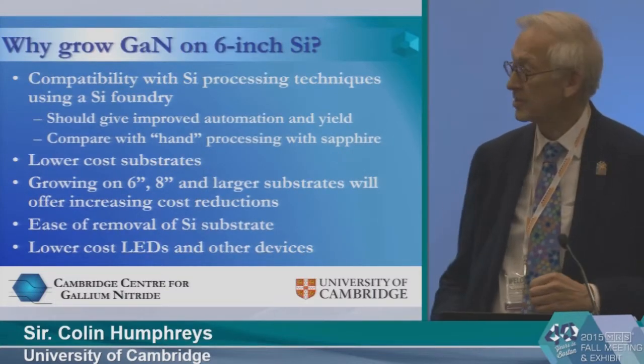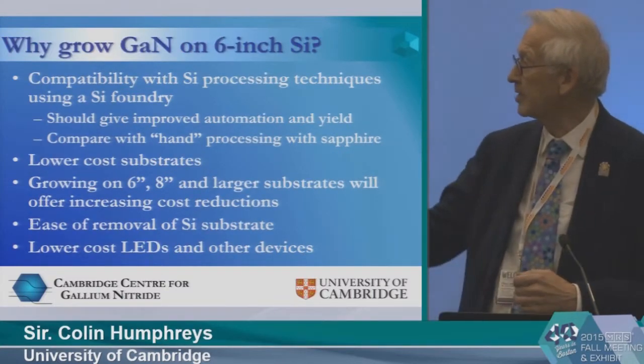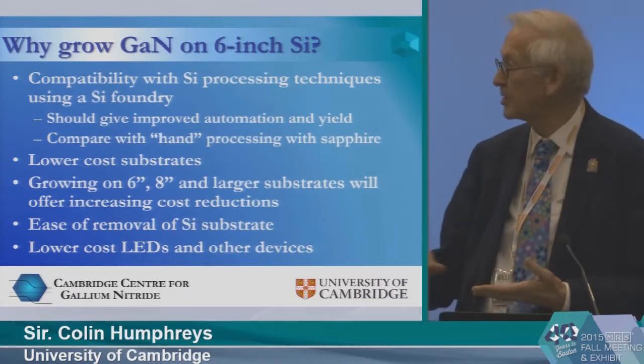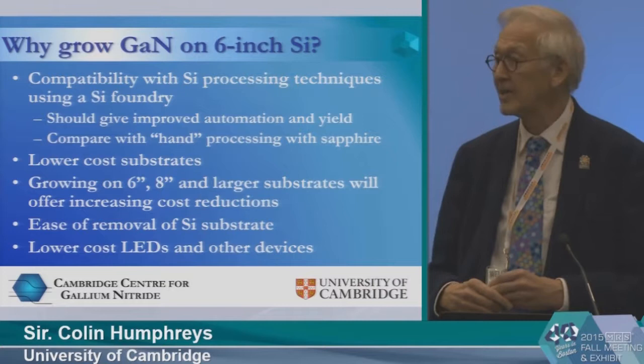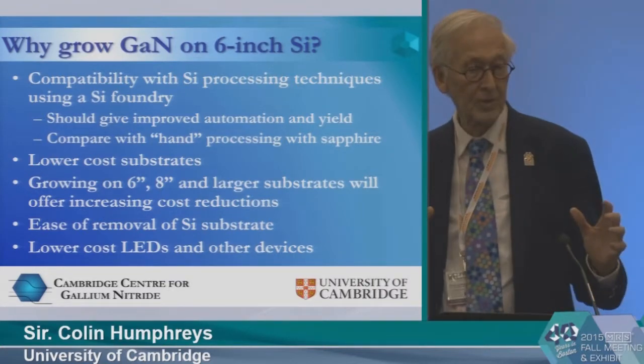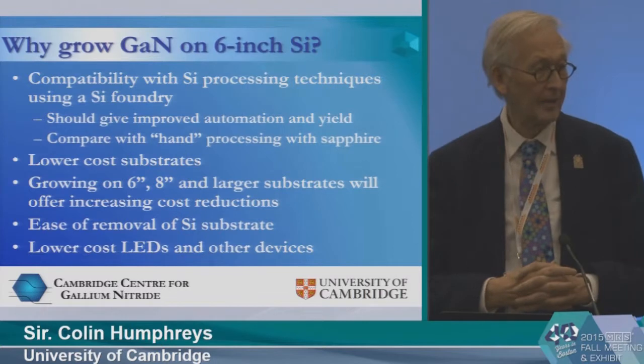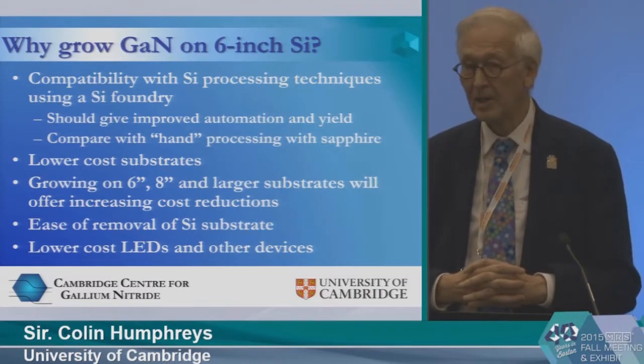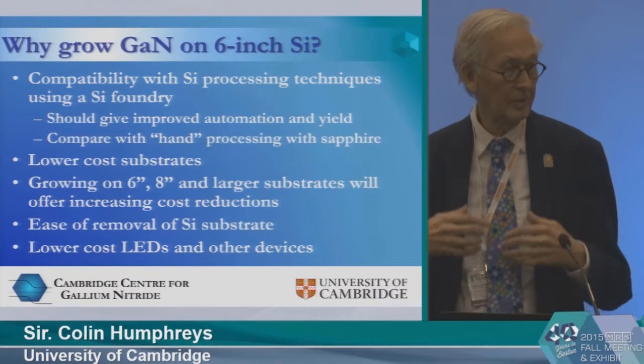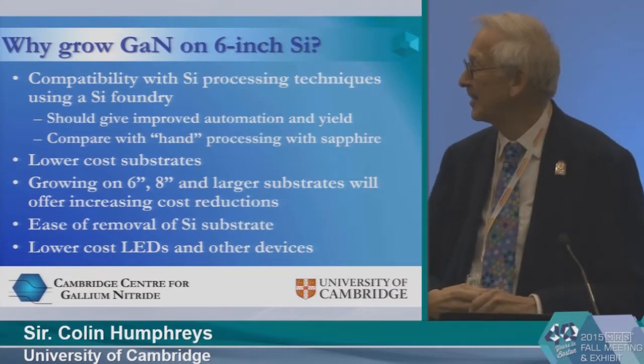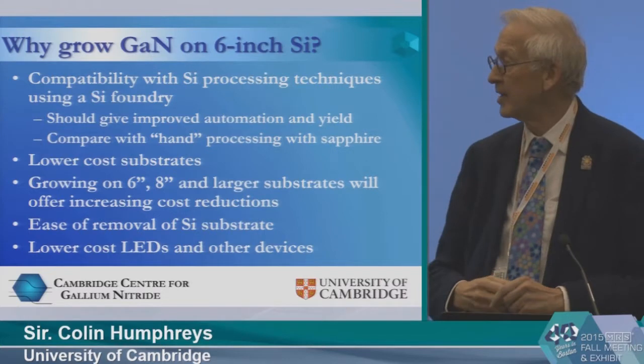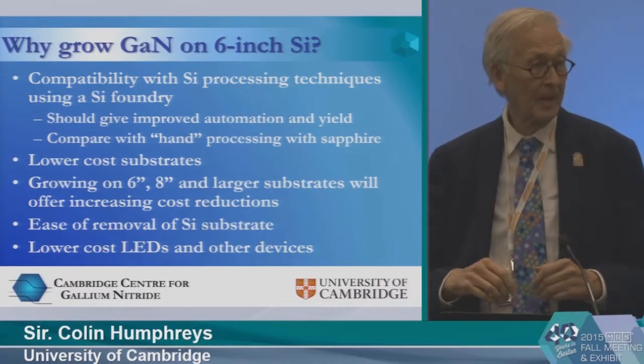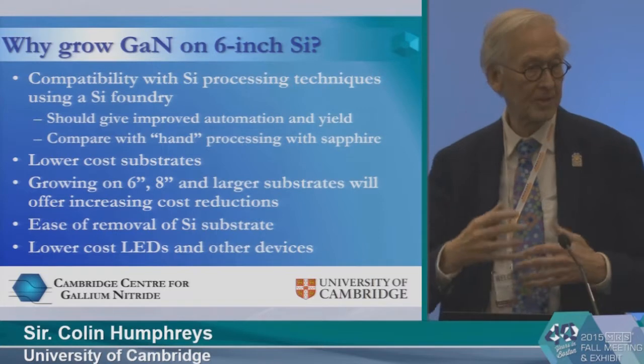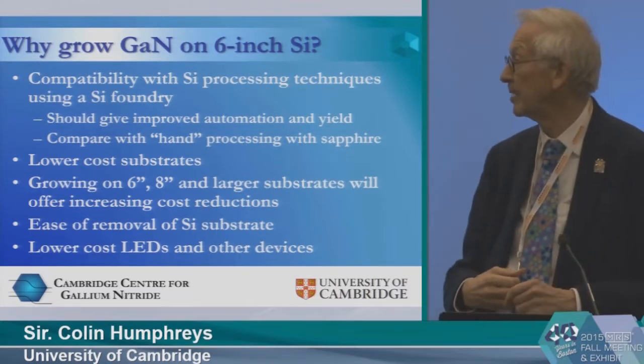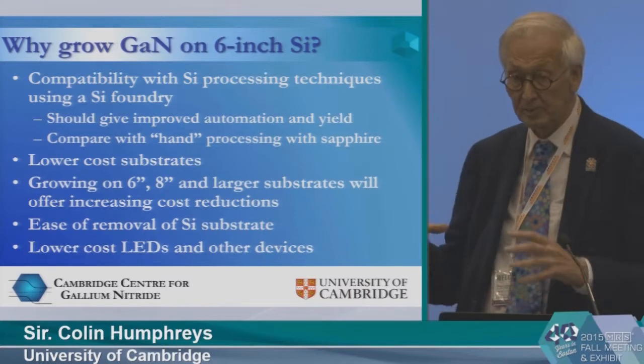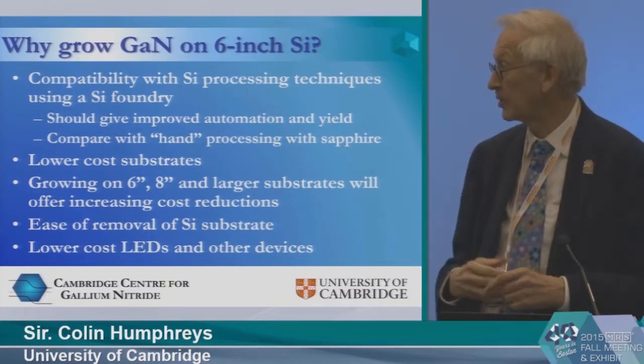So why do we want to grow on 6-inch silicon? I've said some of the reasons already. Another reason is it's compatible with silicon processing techniques using a silicon foundry. Silicon has now moved to 12-inch, so there are a number of silicon foundries around which are 8-inch or 6-inch, which are totally depreciated and there for free to use if you have one of these. The thing about using a silicon foundry is it's automatic and it has high yield, whereas the processing on sapphire wafers tends to be largely hand processing by comparison. And if we can grow on 6-inch, then we can probably grow on 8-inch and then 12-inch for even larger cost reductions.